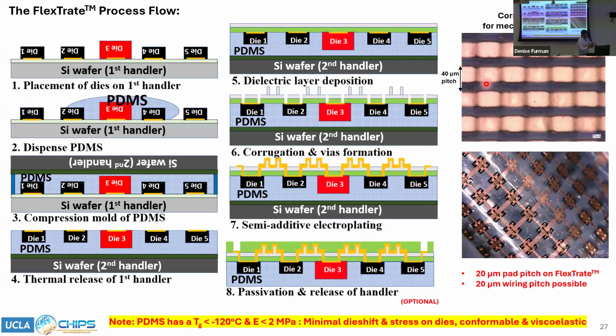So how do you actually do the FlexTrate process? It's very similar to a conventional fan-out process. First you start with a silicon wafer, which I'll call handler 1. You laminate some thermally debondable adhesive, then you flip chip attach the dies with some kind of alignment, and then you pour the molding compound, PDMS. You then compression mold it with a second handler, which also has a thermally releasable adhesive, but with a higher release temperature than the first one. Then you heat this to the release temperature of the first handler, so the first handler goes out, and you get this very flat surface with the dies embedded in the molding compound. And then you basically do standard back end of line processing to define your multiple layers of wiring on top.